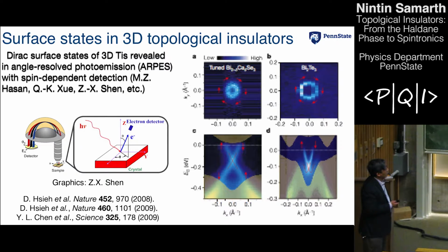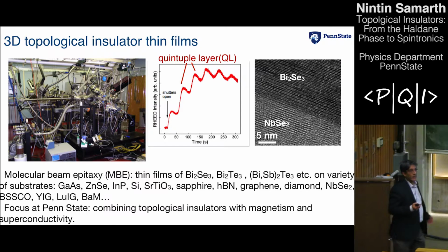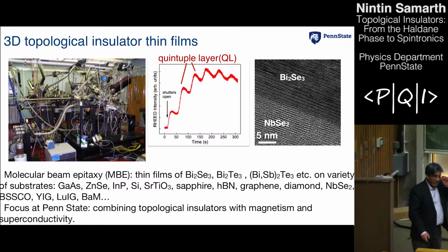And if you furthermore do an analysis of the spin of these electrons, you find that indeed, as you go around the Dirac cone, this is a plan view here of the Dirac cone, you find that these red arrows represent the direction of the spin. So using angle-resolved photoemission, the existence of these materials and these states was certainly established quite early and very, very quickly by a number of groups.